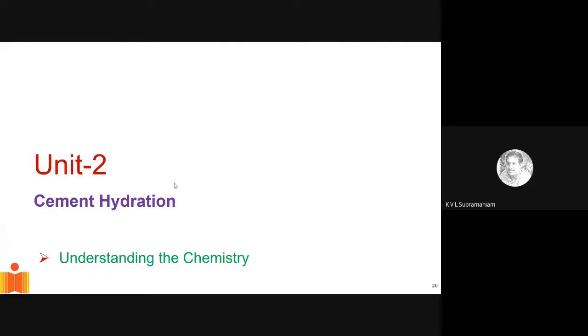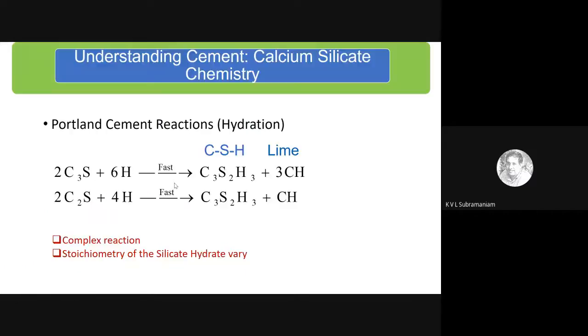So to make any improvements, first we have to go back to the basics. So let's look at cement hydration and the cement chemistry. We know that the two primary compounds of cement which are responsible for most of the properties in cement are the calcium silicates, the tricalcium silicate and the dicalcium silicate. And these react with water in this reaction which we call hydration to give the calcium silicate hydrate. And of course, a lot of lime or calcium hydroxide is released in the process.